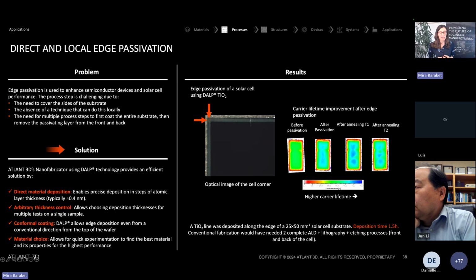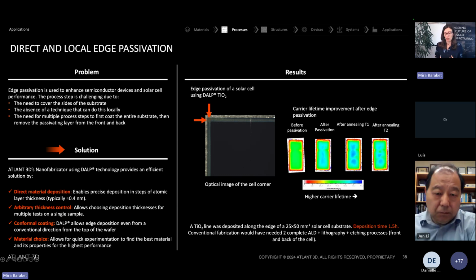So in terms of processes, this example is about local edge passivation. This technique has been used for solar cells, and DALP has been used to passivate the edges of the corners of silicon chips. If you were to try to do this process using standard processing techniques, this would be very difficult, and you would struggle with the deposition on the edge of a surface, because you would have to go through the etching of the front and back side of the wafer, and this would be very costly and time consuming. So in this case, we have shown that we were able to improve the carrier lifetime after the edge passivation only on the surface, and this was done by depositing within a few hours.